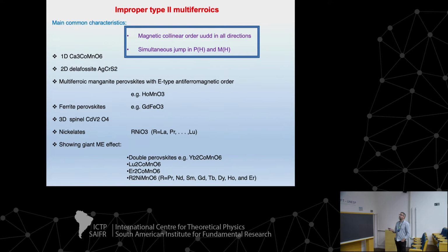And this is improper. Type 2 means improper, and improper means that the magnetic structures are collinear. There is a different kind of multiferroics, the first ones that were studied and discovered, where the origin of multiferroicity is based on spin-orbit effects and Dzyaloshinskii-Moriya couplings. In those cases, magnetic structures are spiral type, non-collinear, in general non-coplanar. This is another class of multiferroics where one of the important characteristics for what I'm going to say today is that magnetic structures are collinear.